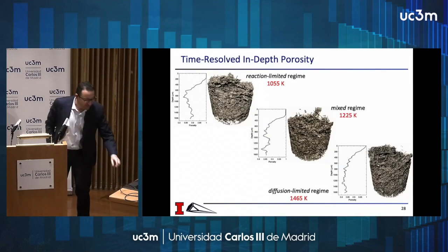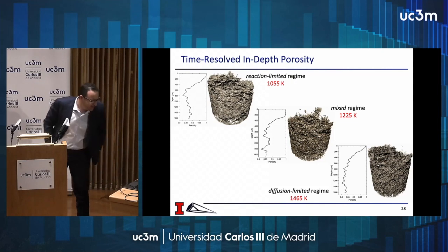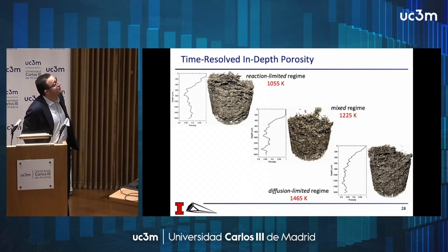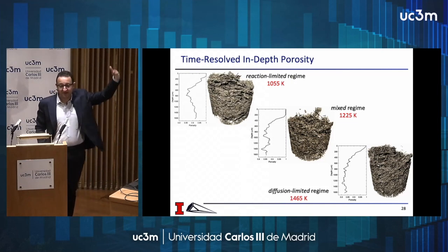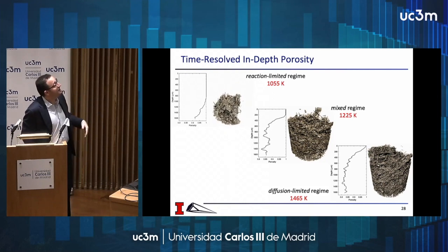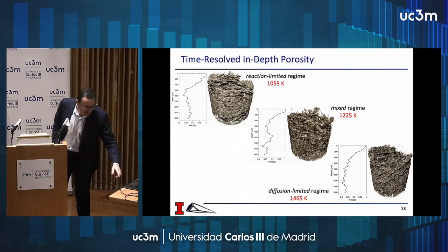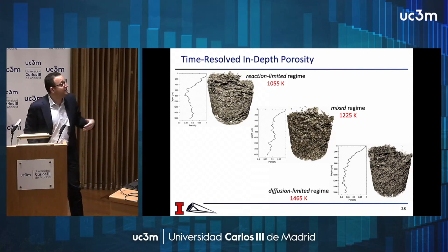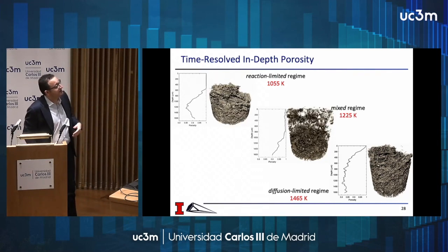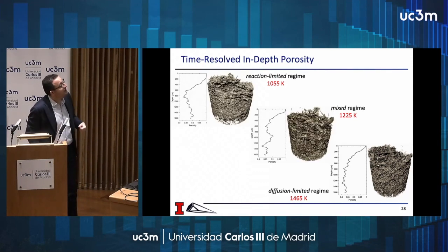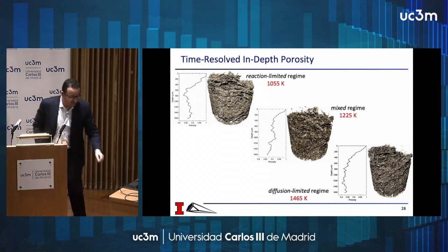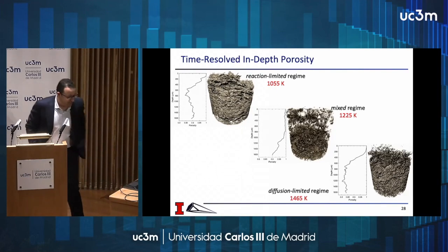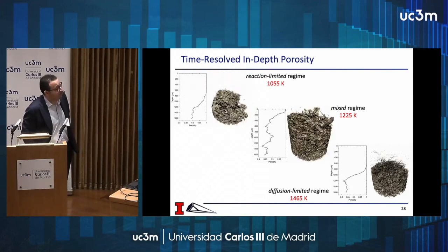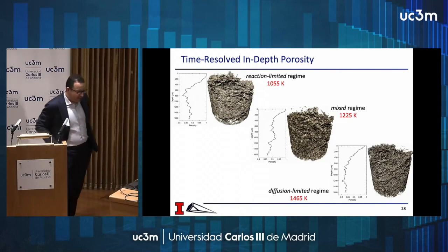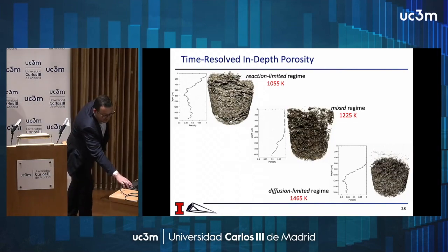Of course you can do a lot more things, and so you can look at the evolution of the porosity of the medium in depth. So again, you see different oxidation penetrations depending on whether you are in the mixed regime, the reaction limited, or the diffusion limited regime.